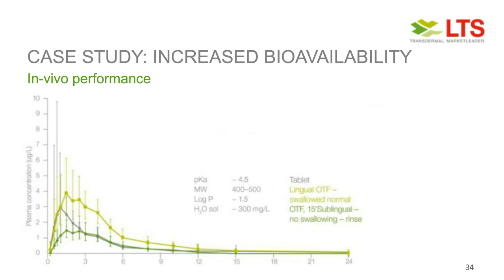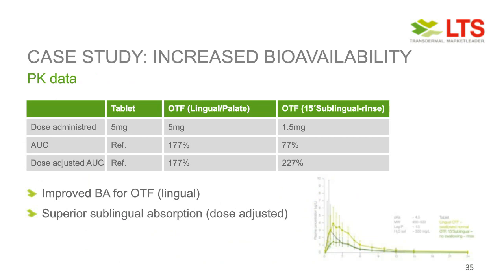So let's have a look at the results. When we administer the tablet with 5 milligrams, this was used as the reference product, the gray curve. And the lingual OTF with the same dose already showed an increase of the AUC bioavailability by about 80%. But then moving from the lingual application to the sublingual application with the lower dose, only 1.5 milligrams were administered. The AUC, of course, goes down to 80% of the reference. But if you adjust this AUC to the applied dose, we end up with a bioavailability or an AUC which is about 230% of the reference. So you can see we can improve the bioavailability for an OTF by the lingual application, but even more, the superior absorption of the sublingual application was also shown, where the dose could be significantly reduced.